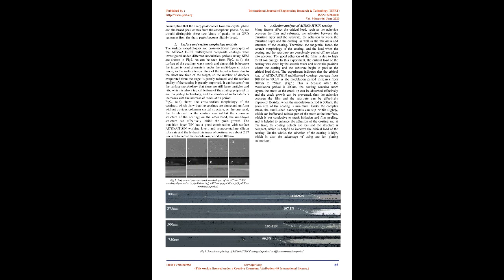After the friction test of the coating, blow off the generated debris. The cross-sectional area of the wear mark is measured by KLA Tencor D300, and the wear rate is calculated according to the formula V equals A/NF. N is the number of friction rings, F is the normal load. The probe pressure was 2.0 mg, scanning speed was 0.05 mm/s, scanning range was 10 mm, scanning distance was 1.2 mm, and finally, the wear rate was obtained.